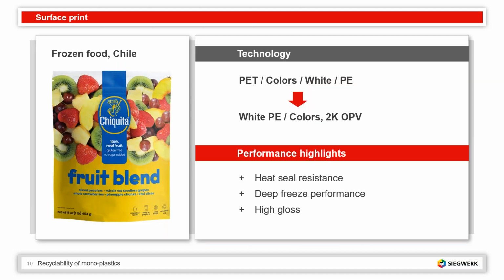And this is not only theory and a nice lab result, but it's also used in practice in the industry already. And I'm showing you here an example from Chile for frozen food. And there, our customer, together with us, has moved a structure PET, PE, with colors and white in between, a laminate, to a surface print on white PE covered with a 2K OPV. And this 2K OPV gives the required heat seal resistance to give the machinability that the customer needs. But it also guarantees the deep freeze performance and the high gloss that is required to bring this product to the market in Chile. So this is already, as I said, in the market, it's done, it works.